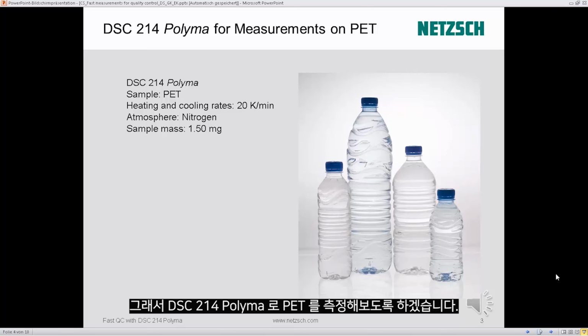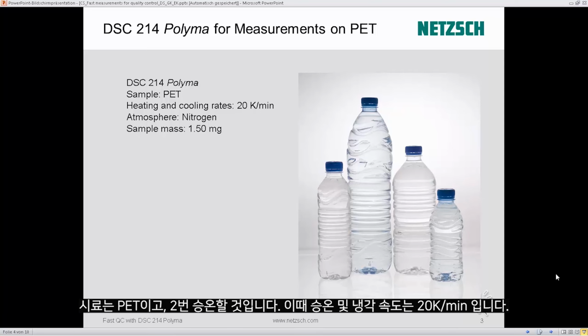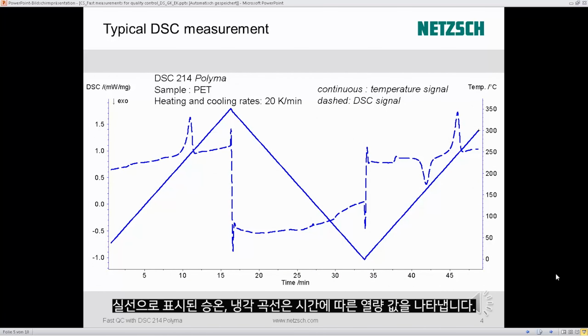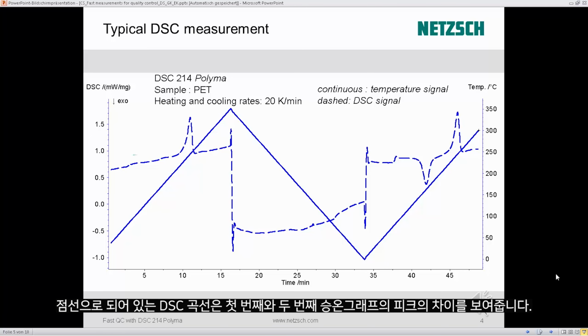Let us start with the DSC measurement on polyethylene terephthalate, better known as PET. Here, the sample was heated twice over the melting peak at 20 Kelvin per minute. Cooling was also carried out at 20 Kelvin per minute. The continuous line represents the temperature signal as a function of time. The DSC curve, presented in dashed lines, shows different effects during the first and the second heatings.